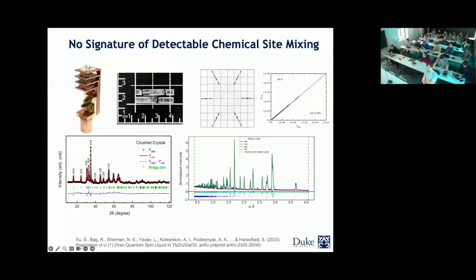That is when we actually started to look at it with neutrons as well, because for neutron scattering, the cross-section is completely different for the two, right? So by doing that, we were able, again, to fit the data. And by fitting the data with no chemical disorder, we were able to get the best results. So these data sets are showing that, at least within the resolution of our experimental techniques, we cannot see any chemical disorder. So that's very good news.